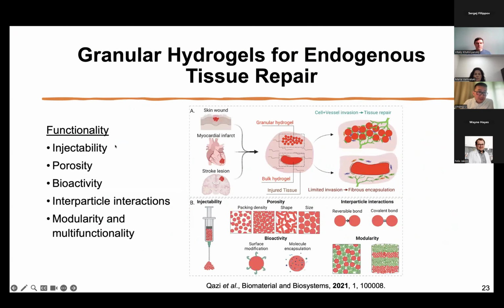For example, you have increased injectability, porosity, and bioactivity. You can apply different modules by modifying the surface with different ligands, which can localize the concentration of your bioactive ligands that engage with the cells. You can also engineer interparticle interactions. You can also change the density, the shape, and the size, and mix and match to achieve modularity. So essentially, you not only increase the surface area, which gives you a lot of opportunity to play around with parameters, but you can also achieve modularity and multifunctionality.